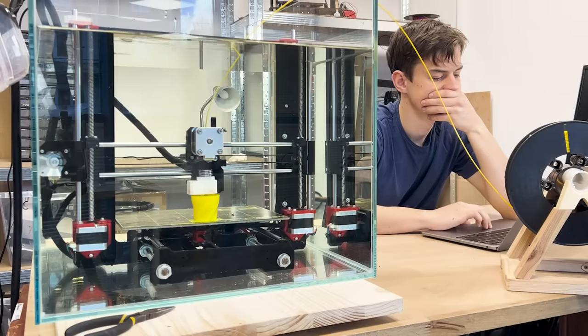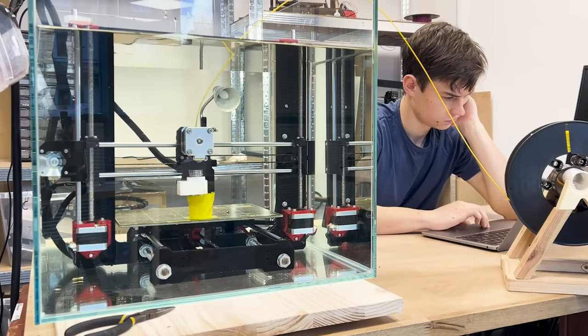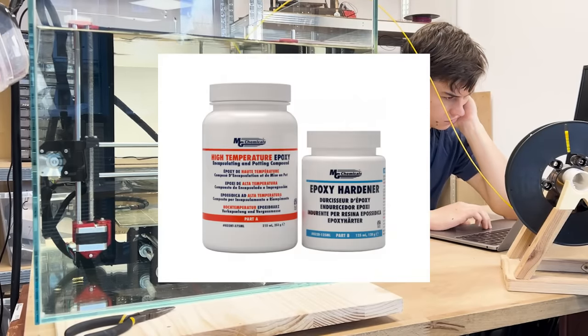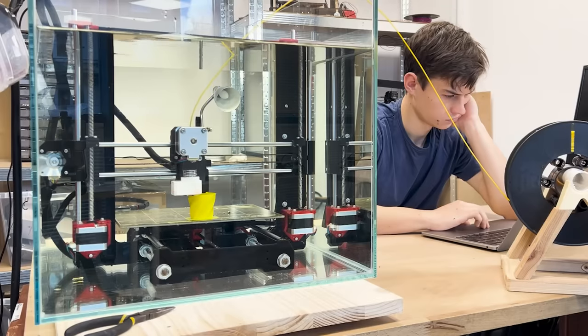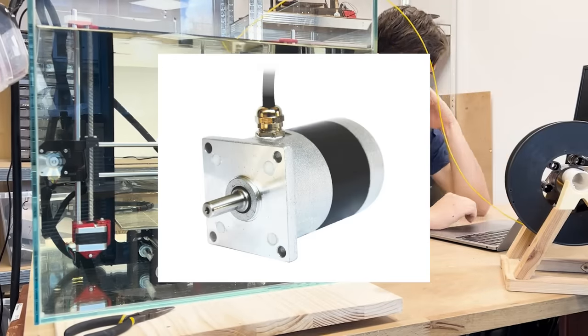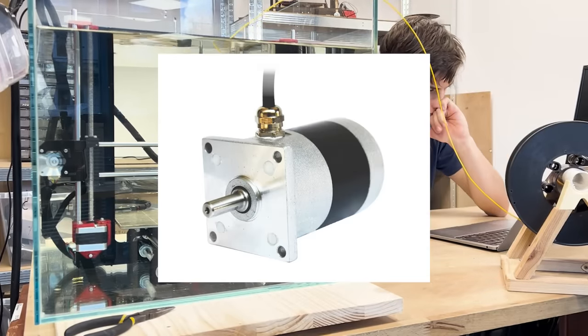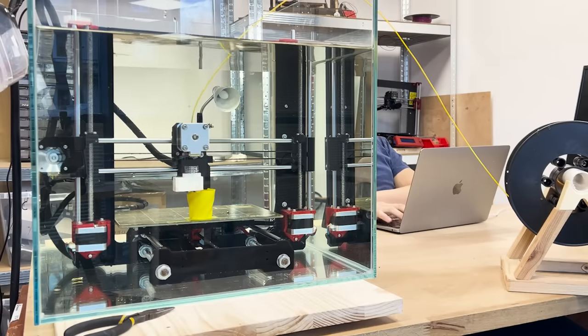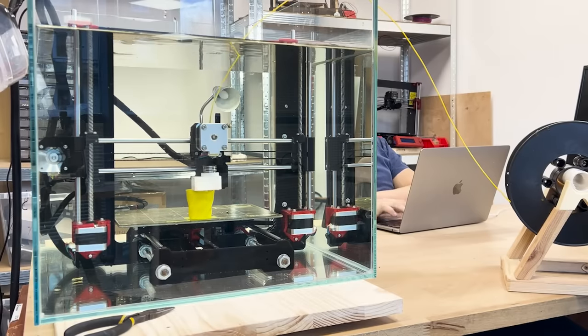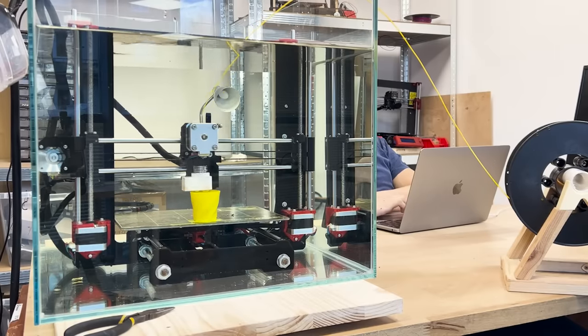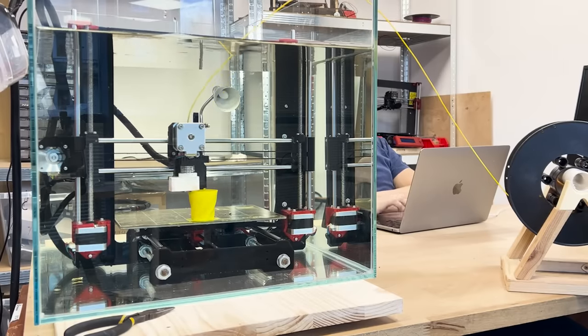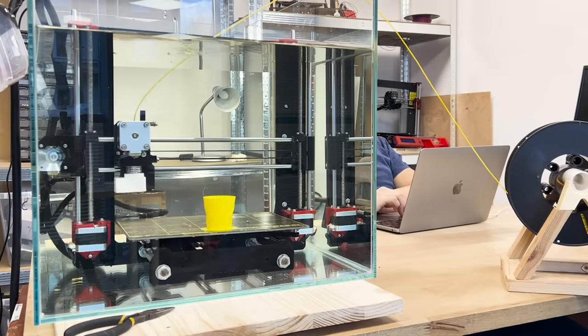Don't worry though we think that underwater 3D printing can be much more reliable with a couple of improvements. One, use a better material for heat block insulation like high temperature epoxy. Two, find a way to make the stepper motors fully waterproof so that they don't start to jump. And three, try to heat up the water just below the glass transition temperature of your filament. This should improve the layer adhesion. Cheers!